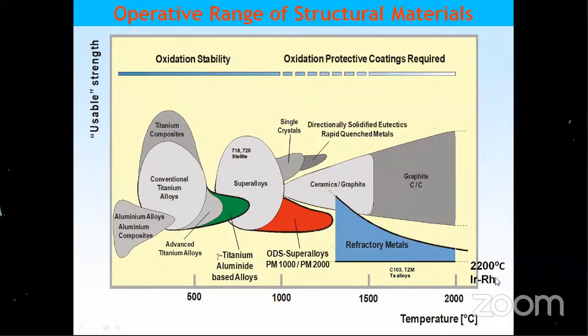And one of my dream materials, which I want to do some work on, is iridium with a rhenium liner. This can go up to 2200 degrees centigrade. It is used by NASA for all their outer space missions. 2200 degrees is very good, because with columbium the maximum we can go to is 1450 to 1500 degrees centigrade. Carbon-carbon graphite composite is used for all reentry vehicles because it can go up to nearly 2000 degrees centigrade, and with silicon carbide coating, it can go further.